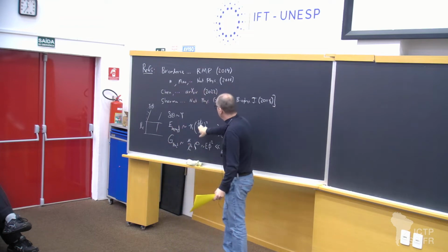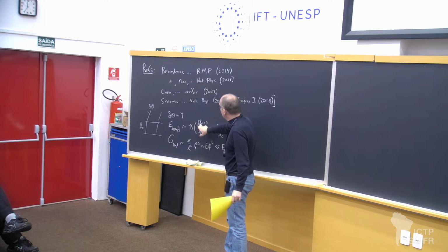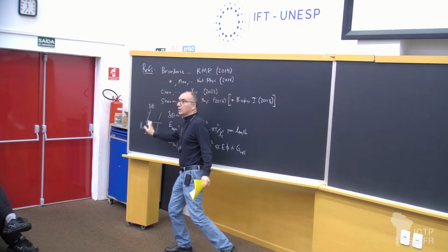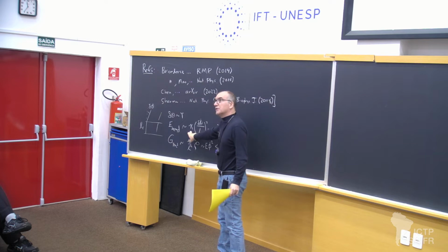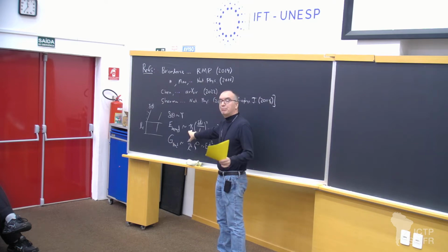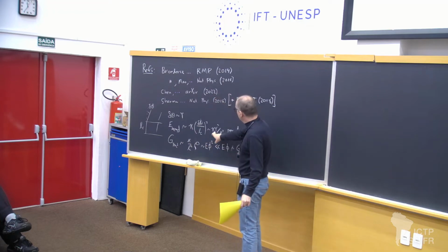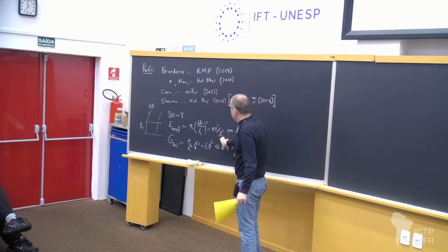The bending, the curvature I should say, would then be the ratio of that angle to the range over which that deflection occurs. Square that and multiply by the bending modulus, and that would be the bending energy per unit length. And so that gives you an energy which goes like gamma squared. Of course, it's going to be linear elasticity. The modulus will be kappa over LC squared.